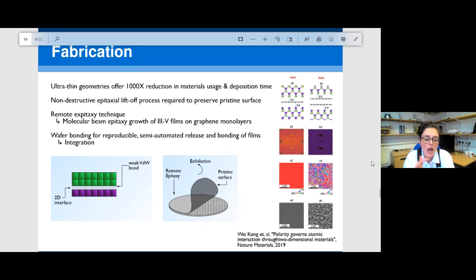However, one of the problems is that epitaxial materials use a substrate for growth, essentially a template for the nucleation of the crystal, and the epitaxial layer forms a very strong bond with the surface of that substrate. So to remove the film, which we have to do if we're going to integrate it with a nanophotonic structure, we've got to break down those bonds, and generally that means a sacrificial etch process, and then if we want to reuse the wafer, a repolish. So it's a frustrating reality that even though we only want 100 nanometers of material, we may end up using several tens of microns through this currently available lift-off process. So there's a real drive to develop new techniques that could enable wafer reuse and enable us to be much more efficient with our use of materials.